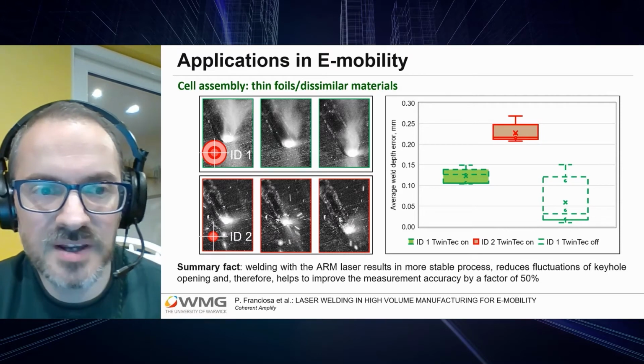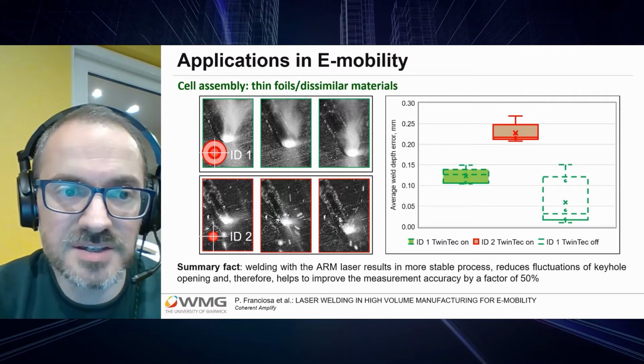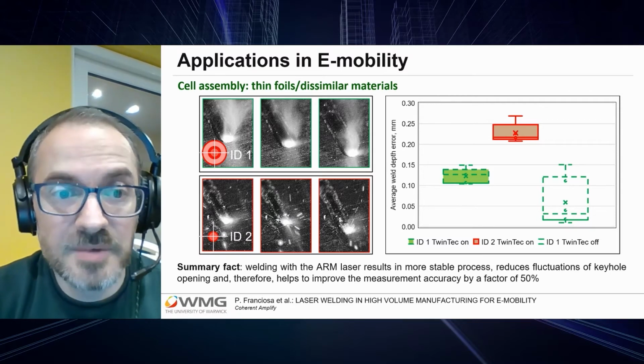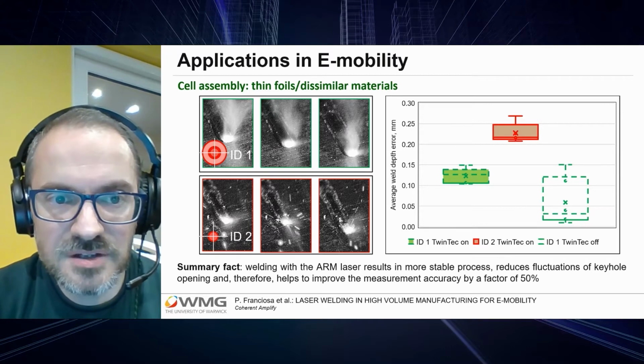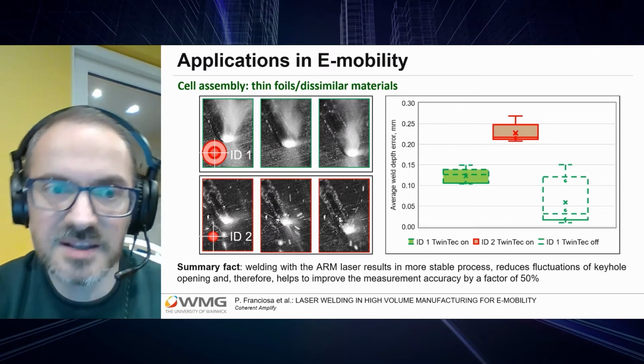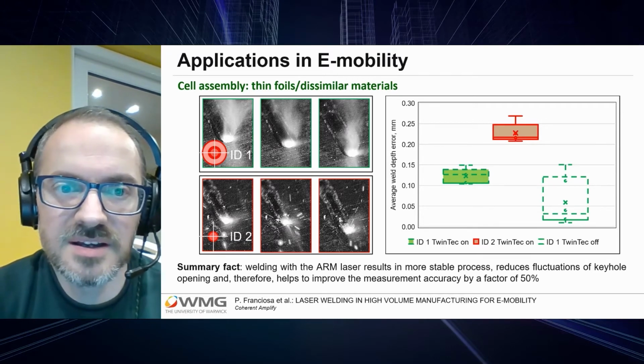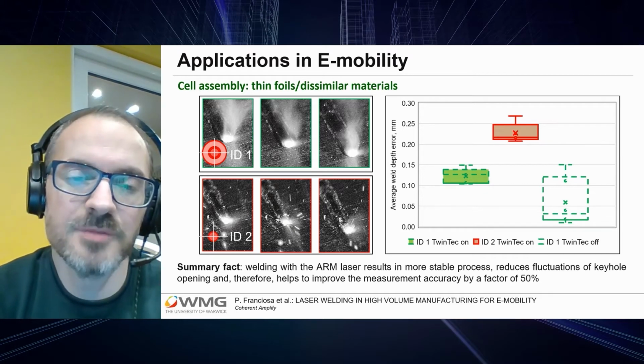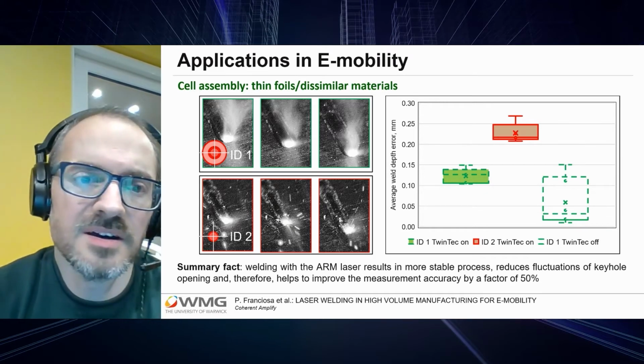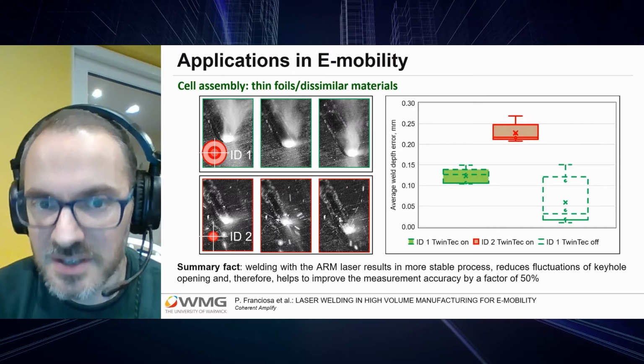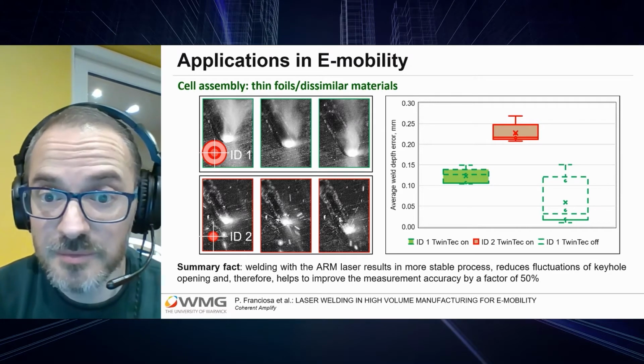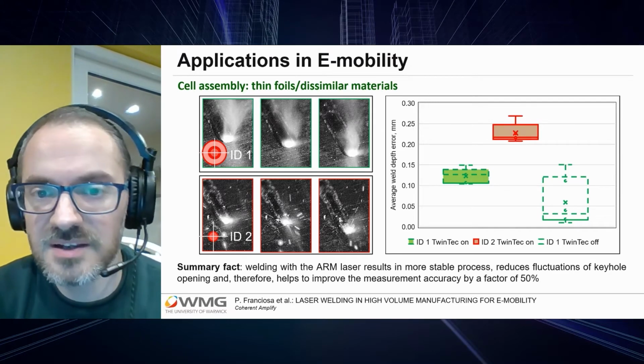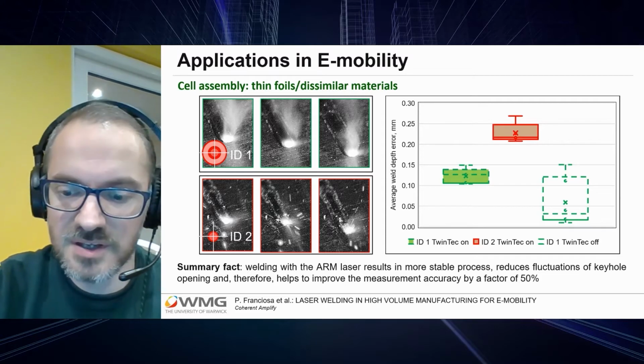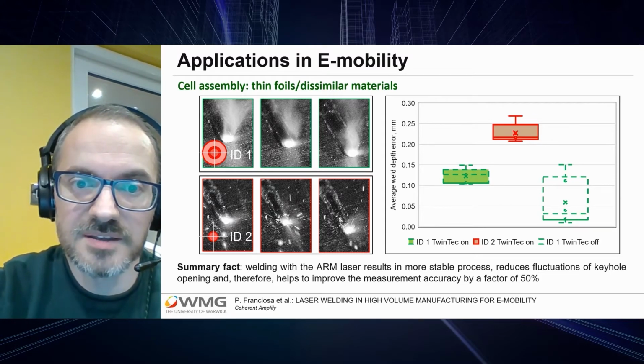So the benefits are quite clear in this application, because in the case of properly selecting the laser power on the ring, the welding process becomes more stable. Because of that, the measurement with OCT is also more repeatable, and the error is significantly reduced, as you can see again from the result on the slide.